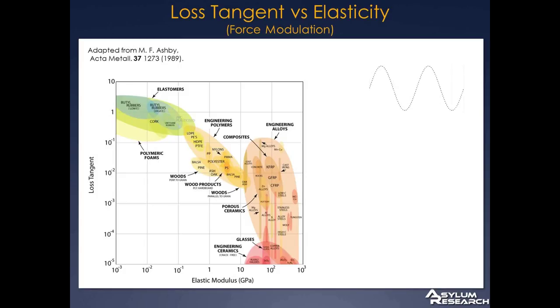So we can think about this graph in terms of materials. What I've drawn on the right-hand side of the screen here is a drive. Think of this drive as your finger poking a sample sinusoidally. It could also be an AFM tip pressed into a sample and driving it back and forth sinusoidally. So we're applying a force or a stress to the material, and the response of that material is plotted in the solid curve here. Now in this case, because the response is in phase, lined up with the drive, we call that an elastic response.